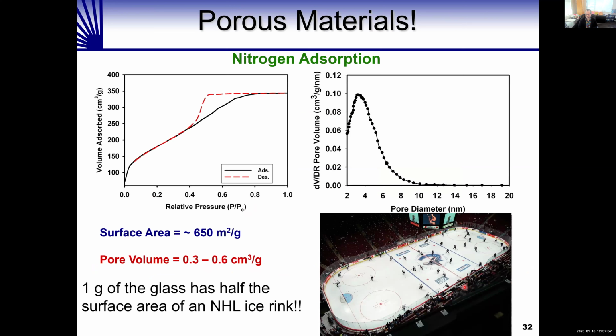This film is very porous. We use a technique called gas adsorption measurements, done at liquid nitrogen temperature, which gives us information about the pore size distribution in the film. We find that the films have a surface area of about 650 meters squared per gram. To give you context, 1 gram of this material has half the surface area of an NHL ice rink—so it's got a very high surface area inside its pores. We can get the pore diameter, and find that the pores are around 4 or 5 nanometers in diameter, which is pretty similar to the diameter of the cellulose nanocrystals we use as a template.